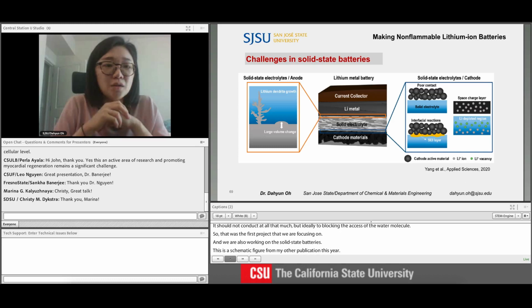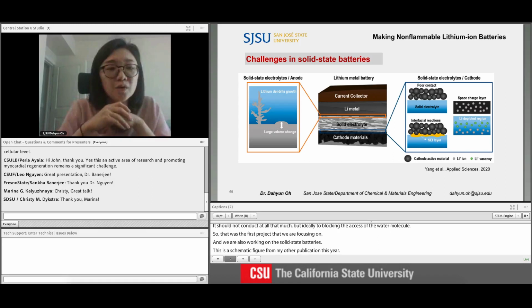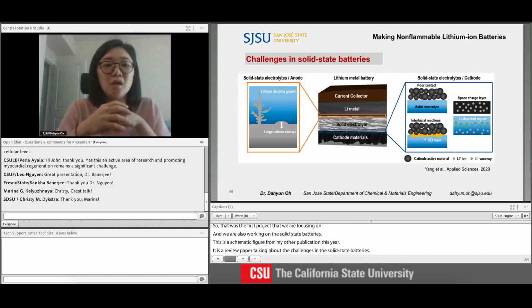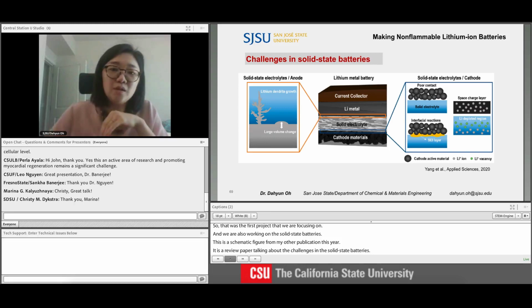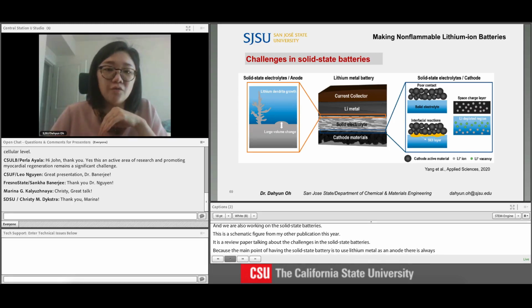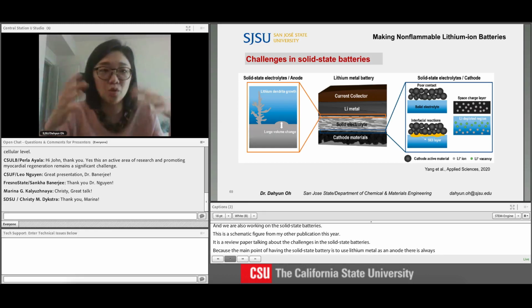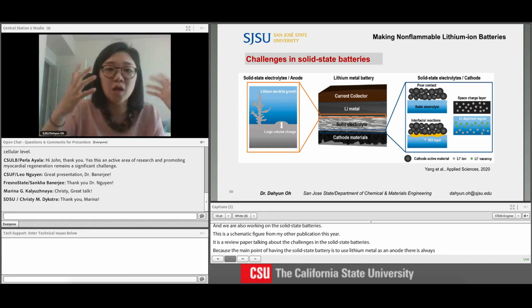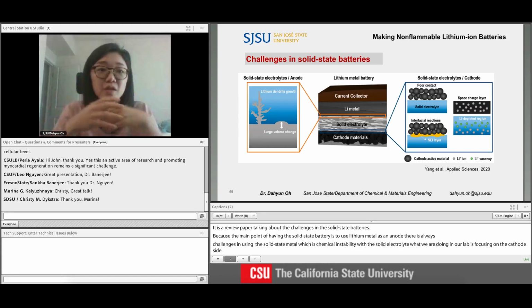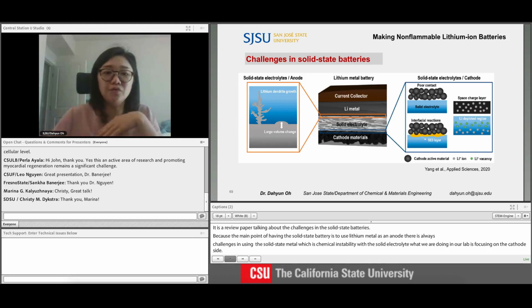And because the main point of having the solid state battery is to use the lithium metal as an anode, of course, there are always challenges in using the lithium metal, which are the dendrite formations or some chemical instability with the solid electrolyte. But what we are doing in our lab is focusing on the cathode side. And among many challenges, such as poor contacts, forming some of the SEI layers, or developing the space charge layer, we're focusing on how we can make a better contact between the solid electrolyte and the cathode side and improve the battery performance.